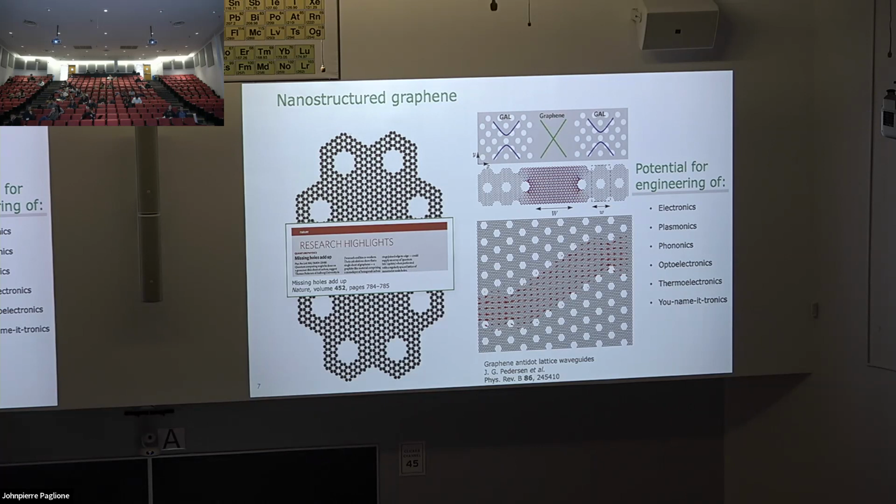I might misremember, but I think if you passivate your graphene with hydrogen, then that helps to preserve the edges and the bonds you're getting there. There are other things you can put on the edges of graphene, like OH and fluorine, for instance. But the go-to in terms of calculation is just to put some hydrogen there, and then things are pretty stable. In theory, right? In practice, it's hard to control exactly the type of edge termination you get for these kinds of things.